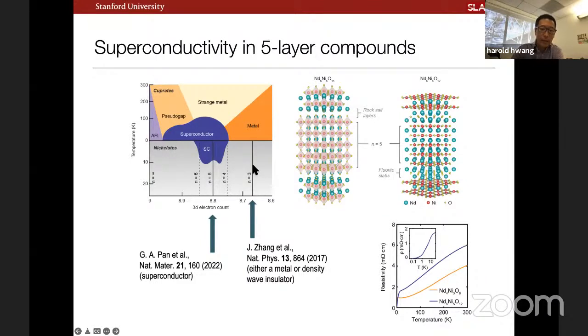And they had speculated that perhaps what they were finding was that they were in the overdoped phase, right? That this natural structural doping, if you will, took them beyond the superconducting dome. They also looked at different versions, say lanthanum and praseodymium and whatnot. And what they generally found was either a metal or a density wave insulator as their ground state. And again, recently, using MBE techniques to stabilize the 5-layer compound, indeed, this system was found to be superconducting. So we start to have a growing materials family, much as you might find in the nickelates or the cuprates, of different layered structures, all built up on the NiO2 plane as the fundamental unit.